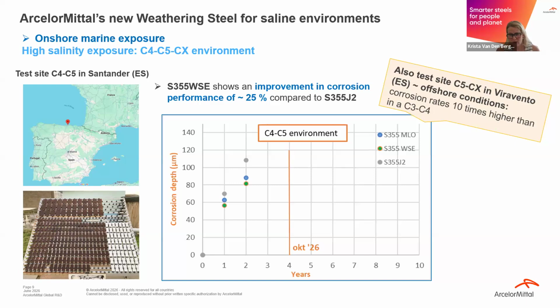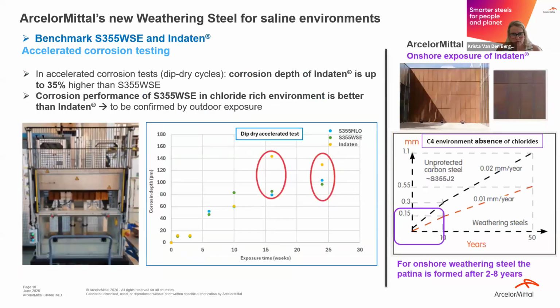We also do an exposure in really severe environments like real offshore, up to CX environment. But here we have to take into account that the corrosion rates are for all materials up to 10 times higher than the current ones in C2, C3 or C4 environments. So for the application, we really see the most benefit in C3 up to C4 environments. So this is all on the exposure and a comparison with the reference structural steels.